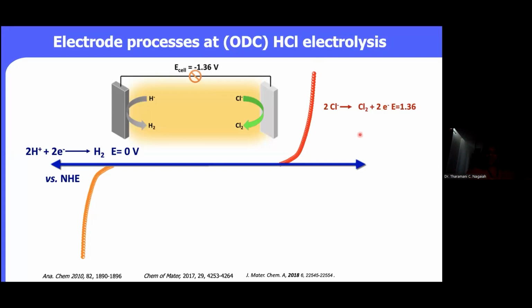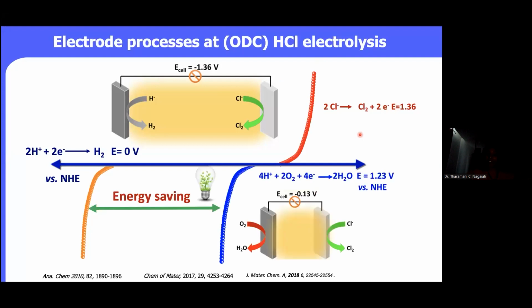Another major problem is that if you want to apply this for industrial application, during an uncontrolled shutdown, the membrane always has a small permeability for the chloride ions. Therefore, the accumulation of hydrogen and also the chloride ions on the cathode causes a serious safety concern. So our approach is that we want to replace the hydrogen evolution reaction by the oxygen reduction reaction. We want to keep the chlorine oxidation reaction constant. So that means we are replacing the 0 volt of the hydrogen evolution reaction by 1.23 V of the oxygen reduction reaction. And we call this process the oxygen depolarized cathode. And we can save almost 30% of the energy.